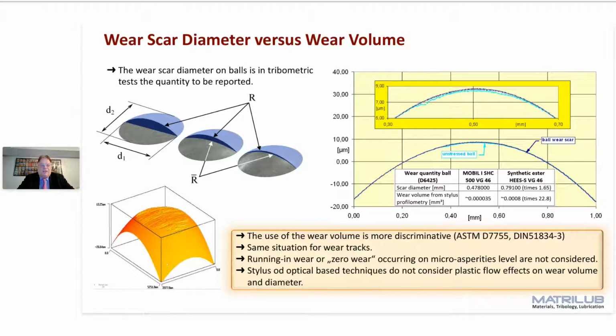The only point is, because you measure the wear volume or the wear scar diameter at the test end, you get no information about running in, unless you have a continuous measurement of the wear length during the test. There is another trend going to zero wear. Zero wear does not mean that the wear is zero, but you are at a resolution limit. And here the wear happens on the scale of microasperities. And it is clear that by wear scar diameter and wear volume, this is hard to determine.